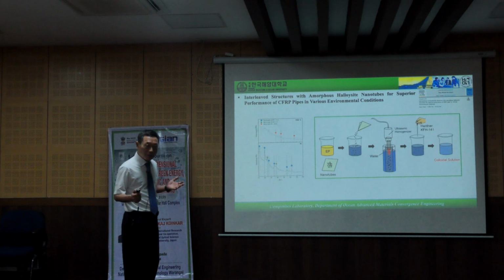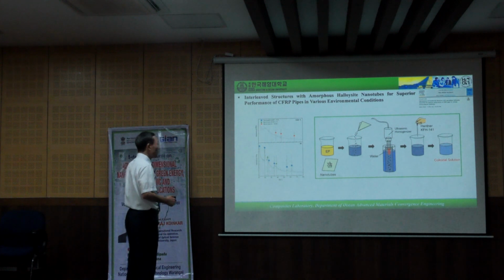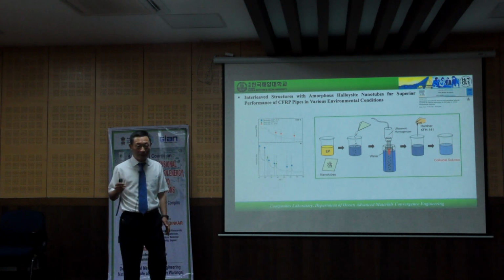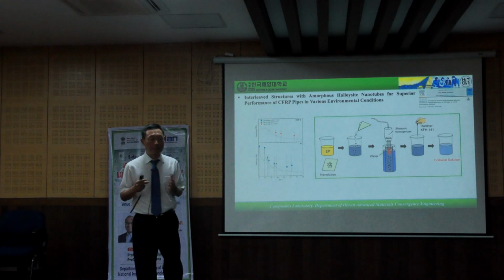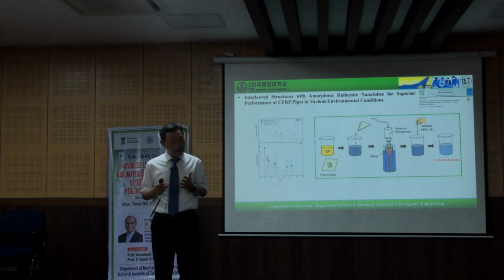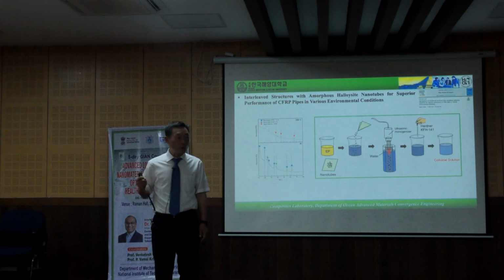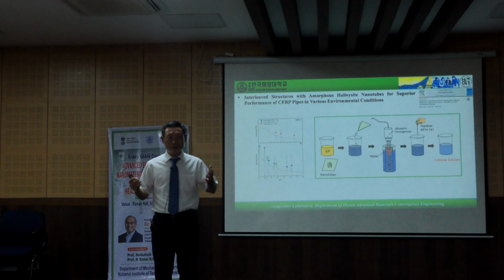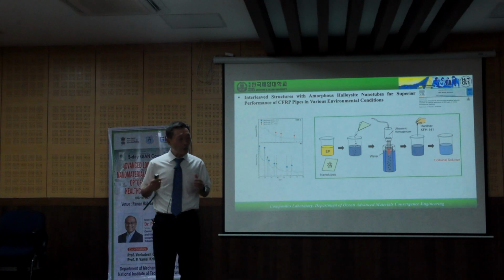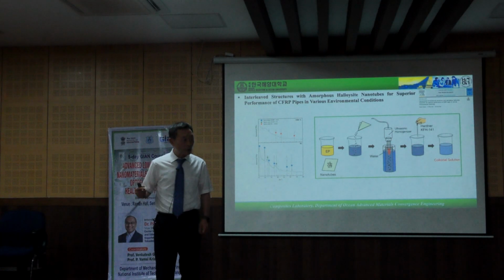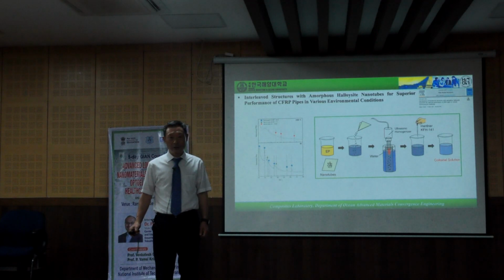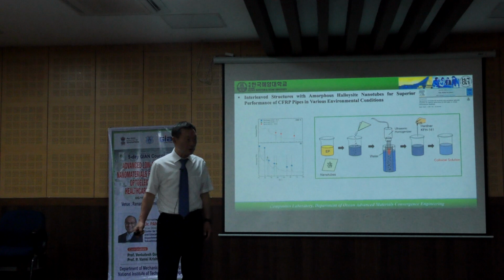As you may know, the halloysite nanotube, by heat treatment, the microstructure will be changed, right? Over 700 and 1000, the structure changes from semi-crystalline to amorphous structure. Very important thing: the water layer will be disappeared.